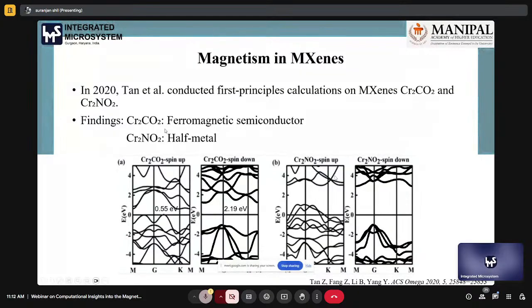And there is another report in 2020 by Tan's group, where they found that chromium carbide, when terminated with oxygen, is a ferromagnetic semiconductor. If you see here on the left side, the band structure of spin up and spin down electrons: in spin up they got a 0.55 electron volt band gap, but for spin down they got 2.19 electron volt. But when it's chromium nitride terminated with oxygen, they got half-metallic behavior. You can see the spin up electrons cross the Fermi level, but for oxygen-terminated chromium nitride the spin down electrons have a band gap here, which shows a half-metallic behavior.